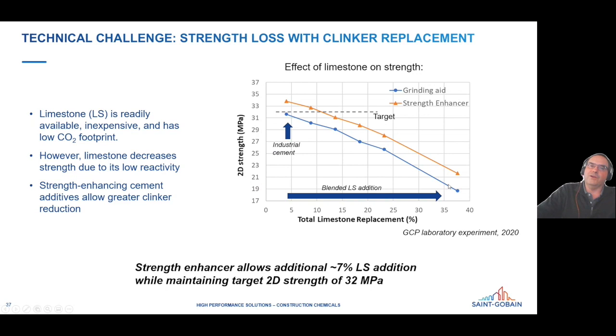So if you use a strength enhancer, then in all these cases, we're getting 2 or 3 megapascals of increased strength. And so the concept is that the customer has a target strength here, but let's say it's about 32 for his cement. And if he adds a strength enhancer, he increases it by a couple of megapascals. And so he can then start diluting it with limestone, and you can add about 7% more limestone and still have the same target strength.